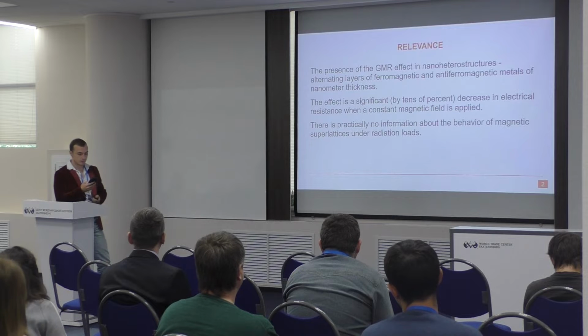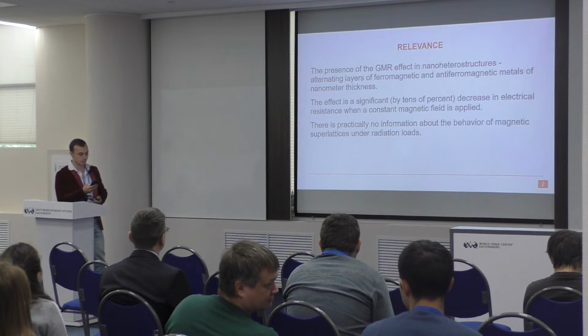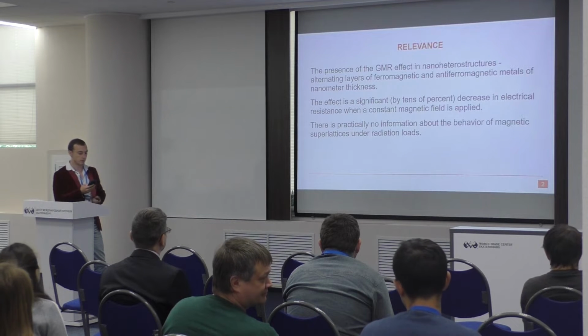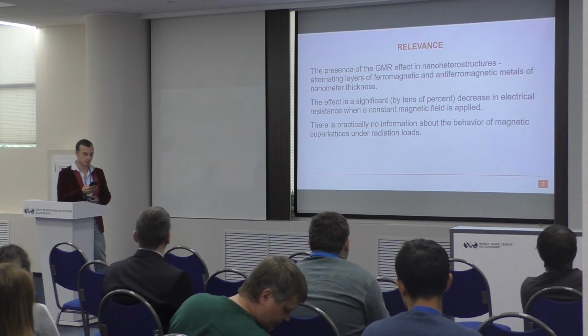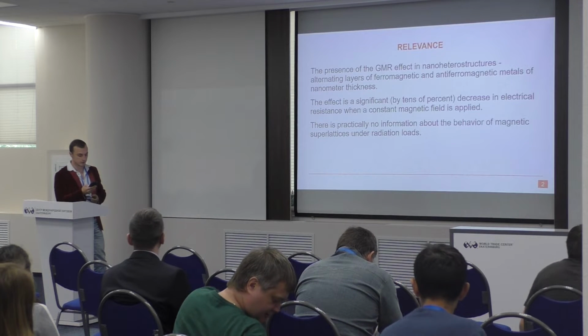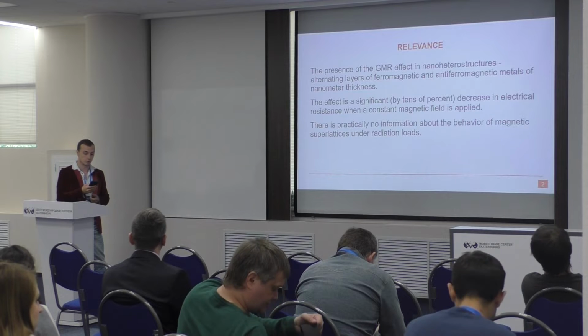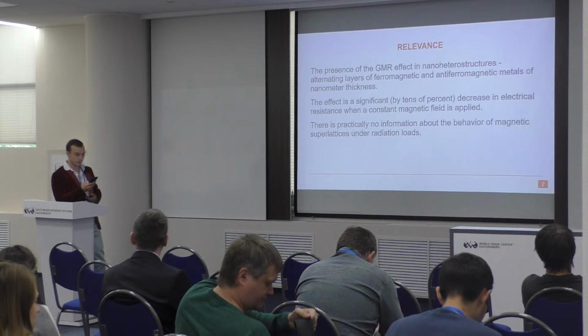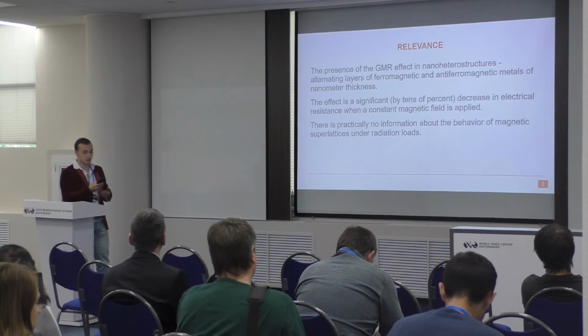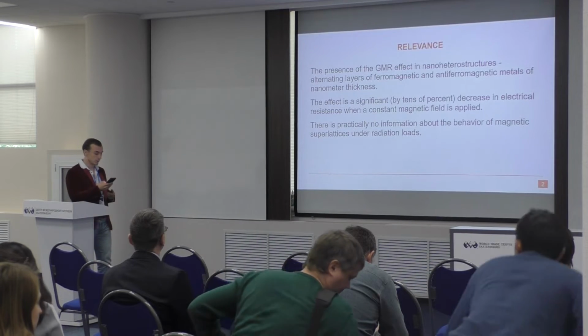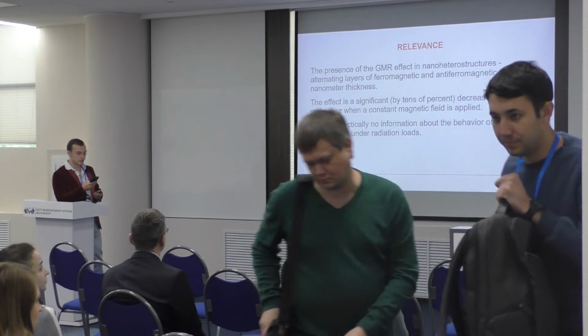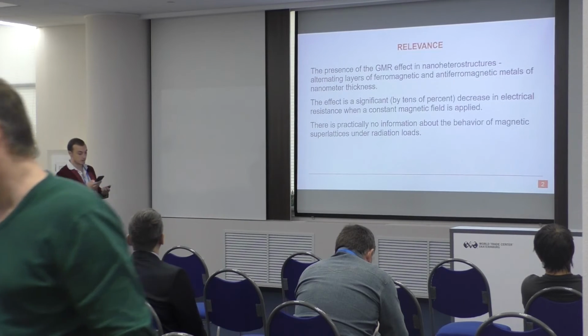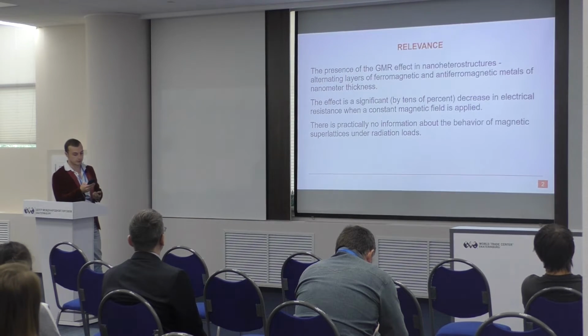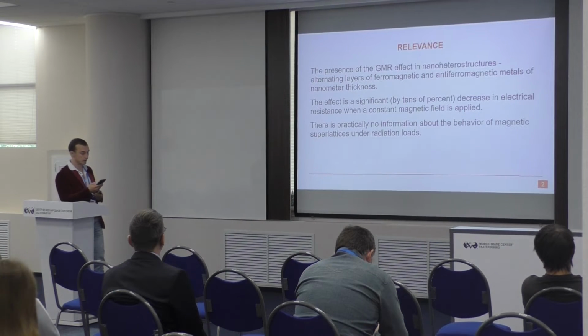Multilayer magnetic nanoheterostructures consisting of alternating layers of ferromagnetic and antiferromagnetic metals of nanometer thickness are in-demand materials for micro and nano electronics due to their characteristic giant magnetoresistance effect, hereafter referred to as the GMR effect, which consists in a significant, by tens of percent, decrease in electrical resistance when a constant magnetic field is applied.